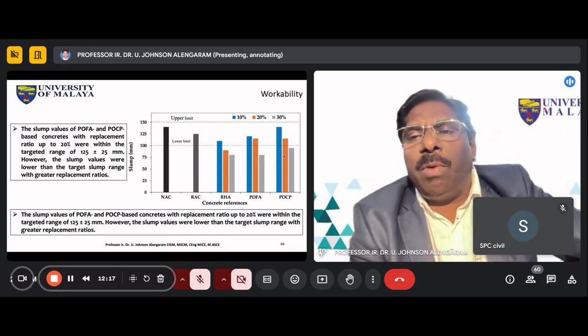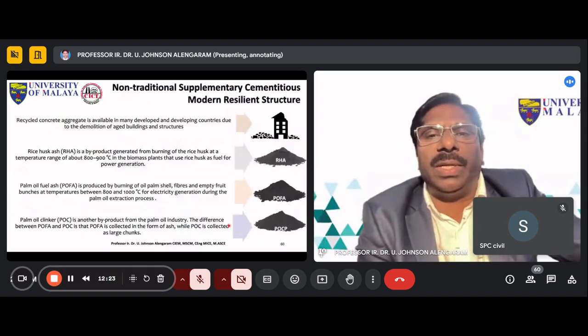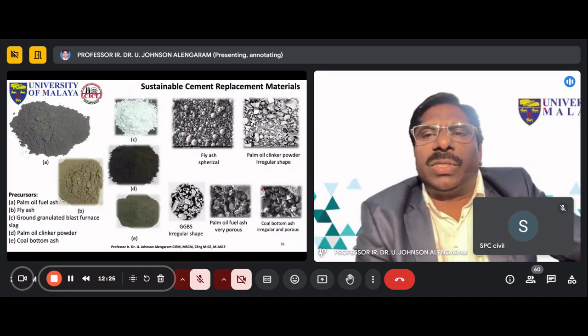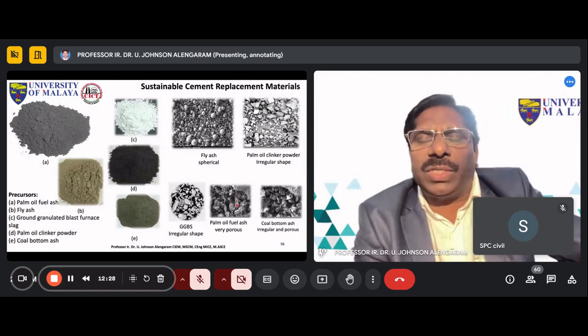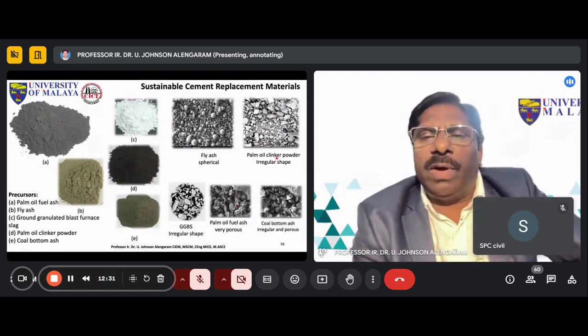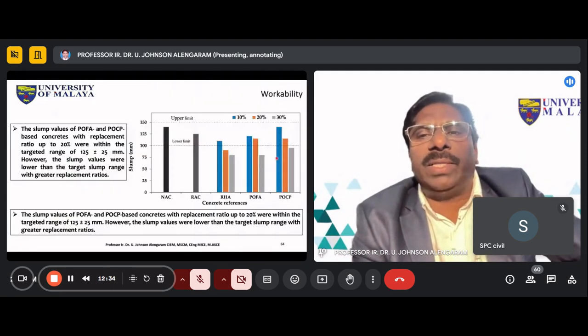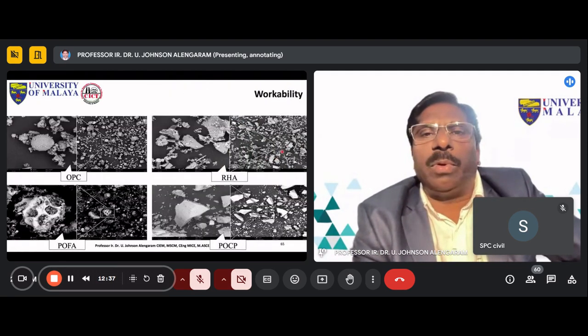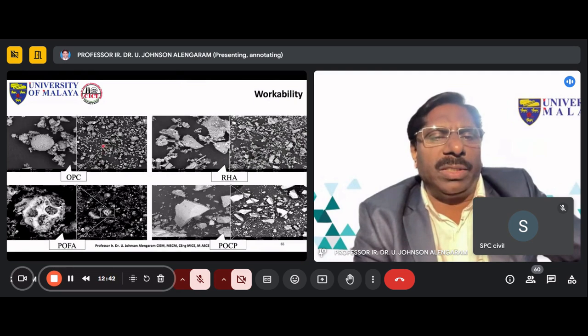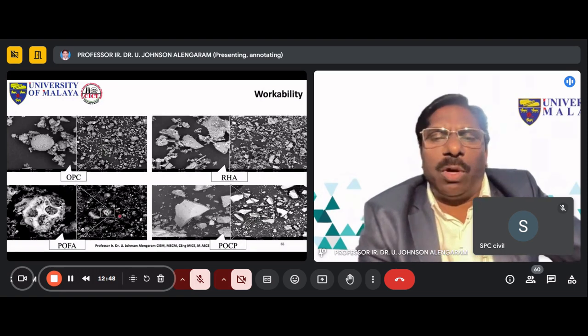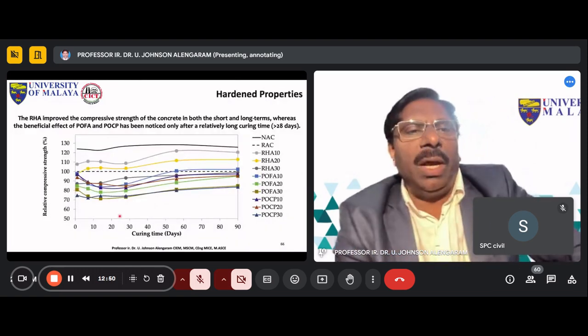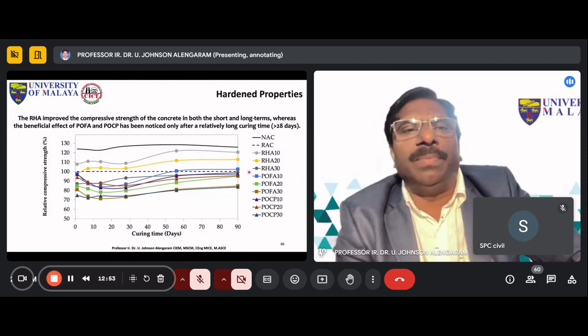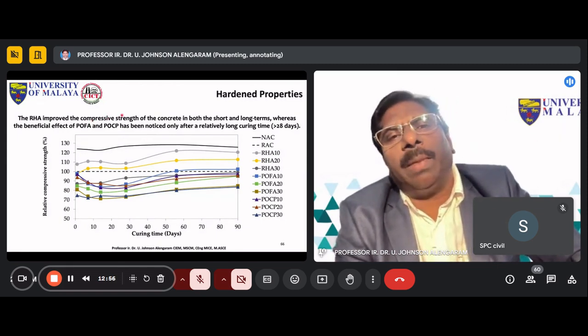When we add 30% of palm oil clinker powder or palm oil fuel ash, the workability is reduced, because, as you have seen here, this material is porous. When it has a porous structure, it absorbs the water, thereby the workability is reduced. That's expected because of the porosity. So I have quoted here, rice husk ash is a porous material, and ordinary Portland cement is not that porous compared to this. So POCP or POFA have a porous structure, thereby they absorb the moisture, thereby the workability is reduced.